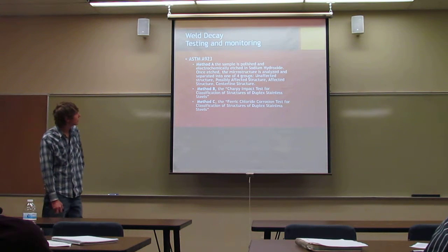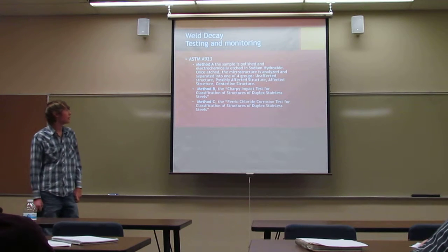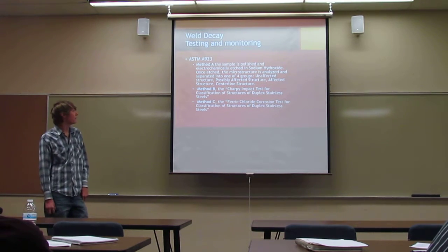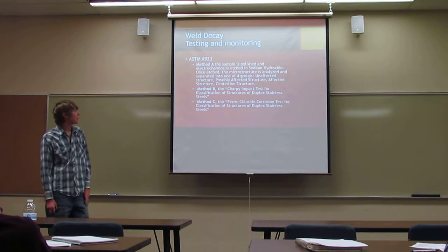Testing and monitoring, I've already gone over. Wait, no, okay. ASTM A923. There are three methods. Method A: the sample is polished and electrochemically etched in sodium hydroxide.